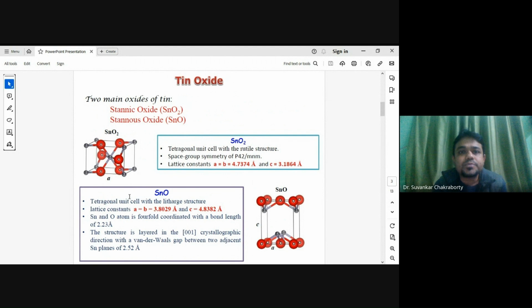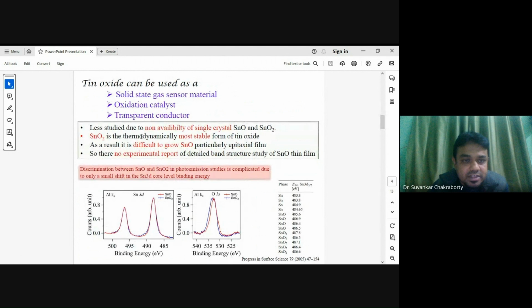Tin has two main oxides: there is stannic oxide and another is stannous oxide. Now, SnO2 is a tetragonal unit cell having a rutile structure, and SnO is a layered structure having a van der Waals gap of 2.52 angstrom. Now, the most interesting thing is that tin oxide can be used as a solid state gas sensor, oxidation catalyst, and transparent conductor.